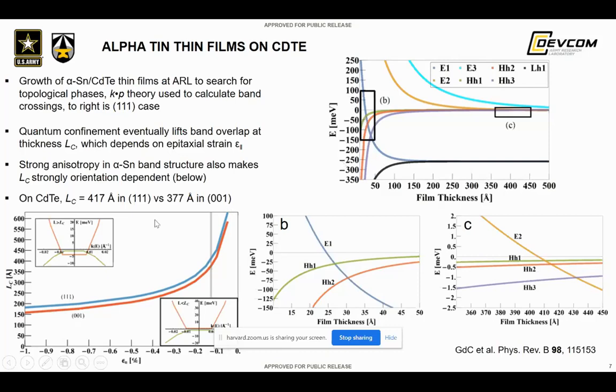Now, the anisotropy in alpha tin is quite dependent on the orientation of the material, which allows it to vary the critical thicknesses quite a bit. So in the case of alpha tin, the critical thickness where you go through the transition is about 417 angstroms in the 111 material, versus about 380 angstroms in the 001 orientation. And these graphs show some typical plots of the overlap as a function of thickness and strain.